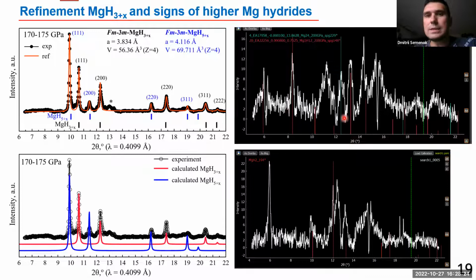But in some other points, we saw something I cannot explain right now. I didn't analyze it in detail because the data is quite noisy, but you can see that in some cases, there are diffraction peaks at low angles, at 8 2theta and even at 6 2theta, which means that in the reaction mixture, it's possible that we have higher magnesium hydrides with hydrogen content 10 or maybe 12.